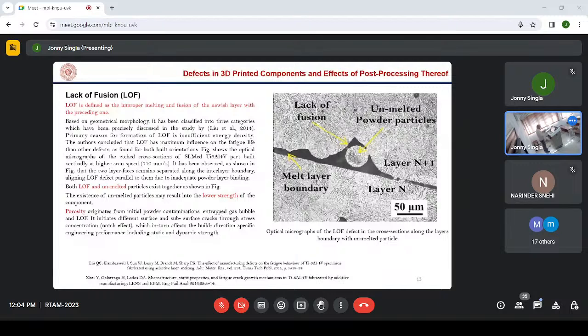discussed in the study. I have given below a reference where this defect, lack of fusion, has been discussed at length. The primary reason for formation of LOF is insufficient energy density function, which we have discussed earlier. The author concluded that LOF has maximum influence on the fatigue life, because whenever there is a lack of fusion between layers, it is a potential source of crack initiation. The defect is found for both build orientations.